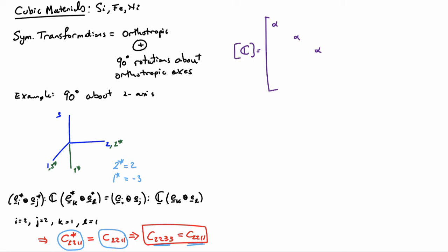So what this is going to tell me, if I start walking my way through the modulus tensor in the 6x6 form, first of all, I'm going to find out that all the diagonal elements have to be equal to each other. So that's one thing that I'm going to find out. And remember, I'm starting with the orthotropic case. So in the orthotropic case, we had 3 different numbers along the diagonal in the upper 3x3 block. Using these rotational symmetries, we find out that those 3 numbers actually have to be equal to each other. We also find out that the off-diagonal elements have to be equal to each other. In fact, that's what we've just proved here, or started to prove here.